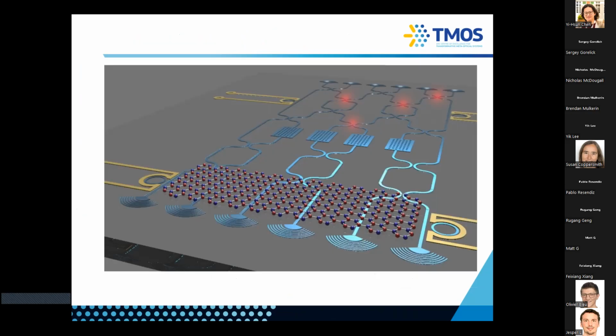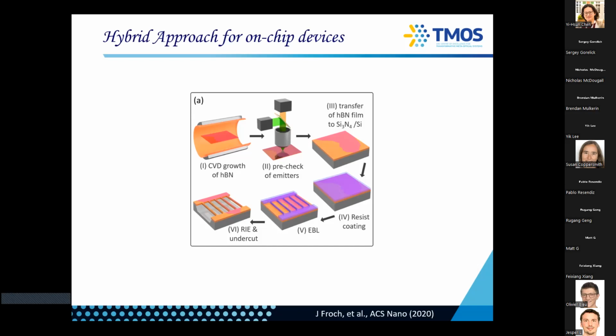All right, shifting gears towards what you can do with these emitters now. Obviously we have a 2D material, so I will show you one result of how we can integrate these emitters with waveguides or a photonic crystal cavity. This is the vision of how we want to do it: many waveguides, and then you put hBN on top, hopefully with identical emitters, to generate cheap, indistinguishable photons. So how do we do it? As I mentioned, we can grow using CVD a very high density of emitters. We grow our hBN flakes and then transfer them onto silicon nitride.